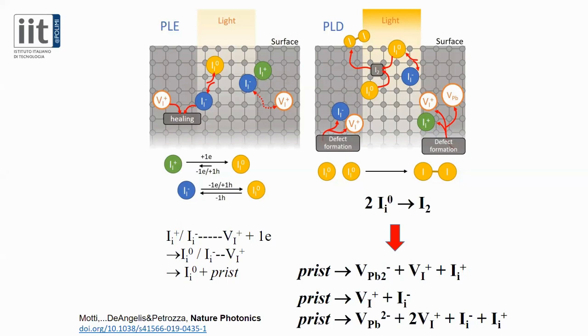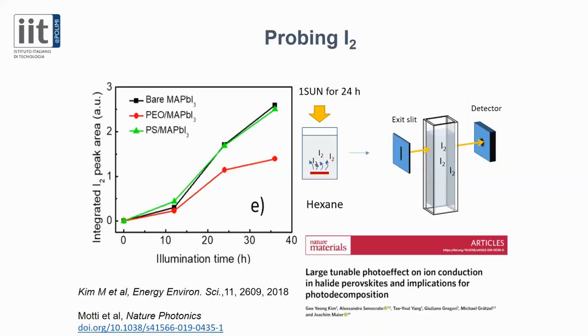I2 doesn't like to be in the bulk and will travel towards the surface, where it will get stuck on a site due to the undercoordinated lead. And in this situation, the I2 can get out and will trigger a catastrophic reaction, which will form more and more defects in the bulk. If we passivate the surface in the proper way and we heal the surface defects, I2 won't be able to escape, and we go back to being left only with the photo healing mechanism. And we proved it experimentally, probing the I2 release in solvent when we illuminate the thin film of perovskite, and we can see that when we passivate it, the I2 is strongly reduced.